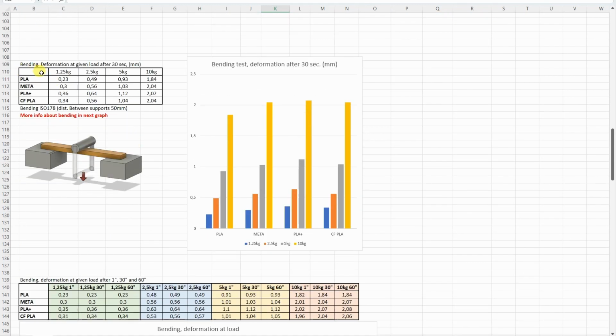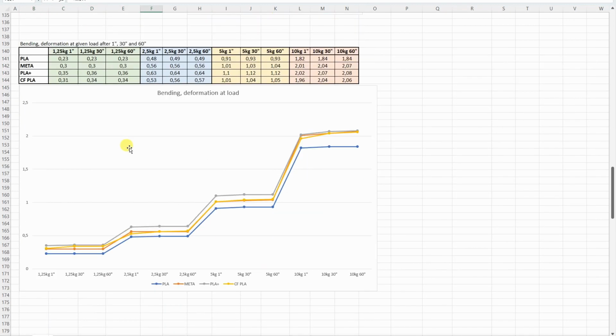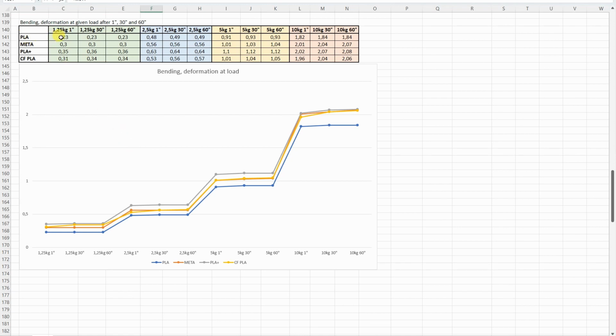And now the bending test, I think this is the most valuable information. Here we can see only the deformations after 30 seconds, and this is what you can see in the video too. But I believe that more useful information is this. As you can see, I recorded the deformation after 1, 30 and 60 seconds. If something is horizontal, then it is good. If we have something at an angle, like here, that means it creeps and the deformation is present even after 1 minute. Smaller values are of course better, so in this test the regular PLA performed the best.